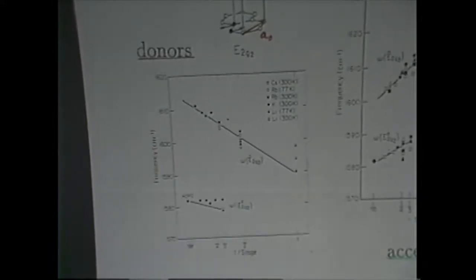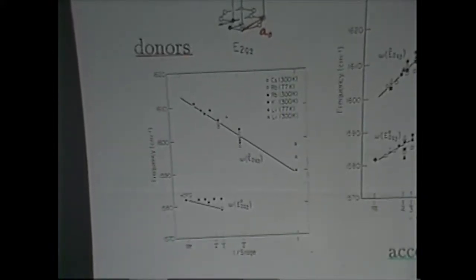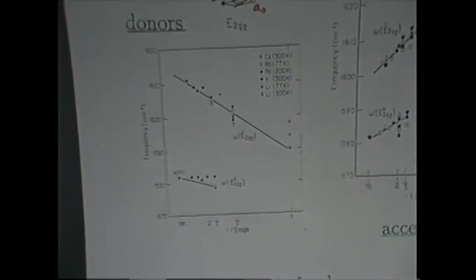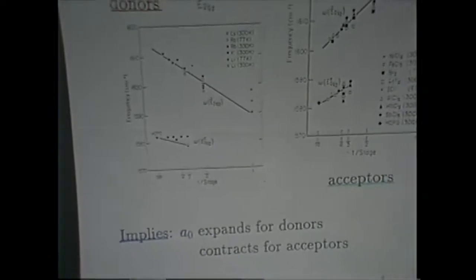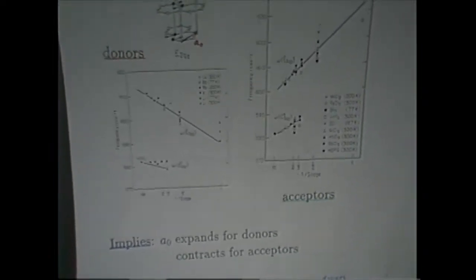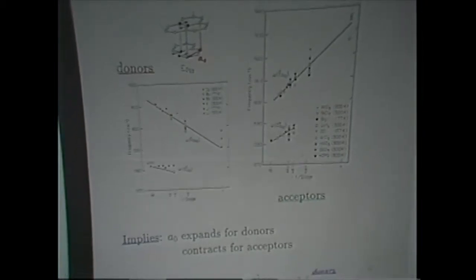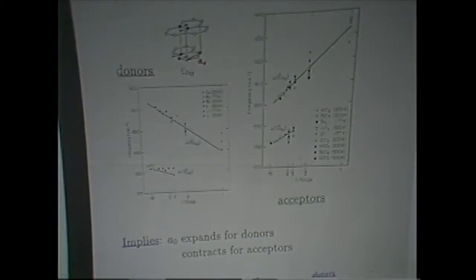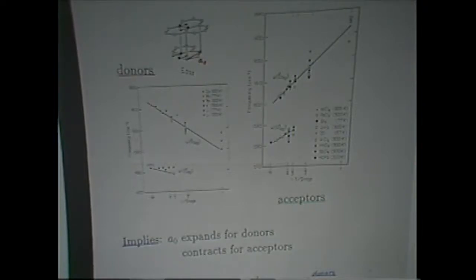Now, this is the one that we could understand from what had been done in the literature on measurement of lattice constants. You have a donor compound, charged from the alkali metal, goes into the graphite layers, it expands the lattice constants, makes the modes soft, and therefore you have a decrease in phonon frequency. Very, very understandable. If that's the case, then the opposite should happen in the acceptor compounds, that the addition of intercalant should sap up electrons, should take electrons away from the graphite layers. Therefore, the lattice constant should contract, and therefore you should have a stiffening of the mode. And that's what's observed. But the experiments hadn't been done, so a master's thesis was generated.